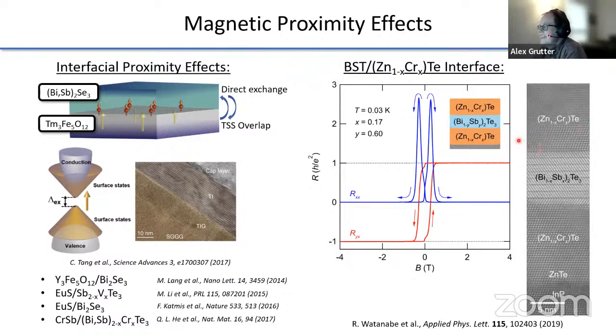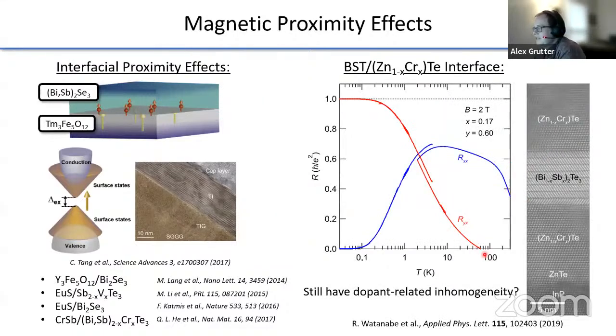Now, one of the really interesting things about this system is that it's got tellurium-tellurium bonds across the interface. And this is thought to be a really important part of the approach, and part of the reason it succeeded is that potentially the tellurium-tellurium interface gives you a very nice alignment of your bands across the interface and a stronger interaction. But on the other hand, the quantization temperature is still unfortunately rather low. Let's say around, well, certainly below 1 Kelvin.